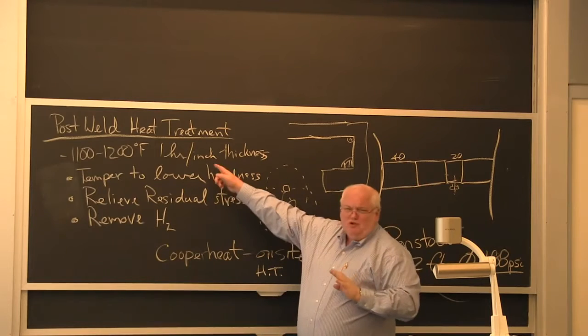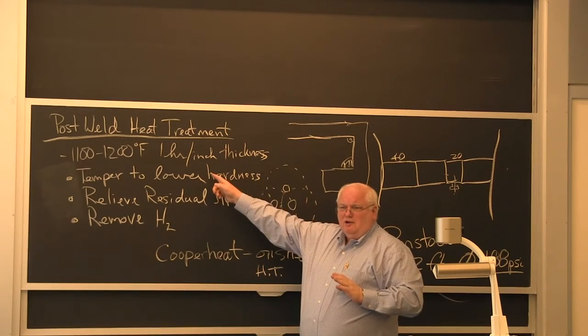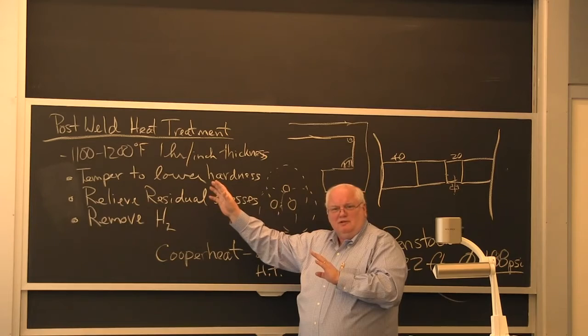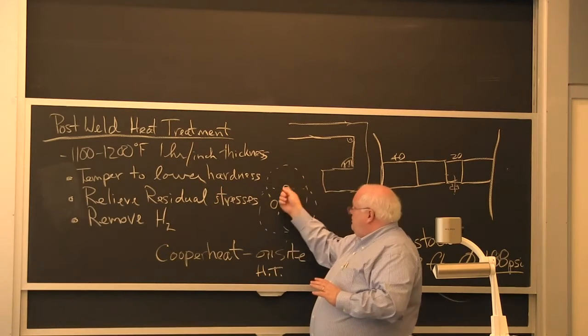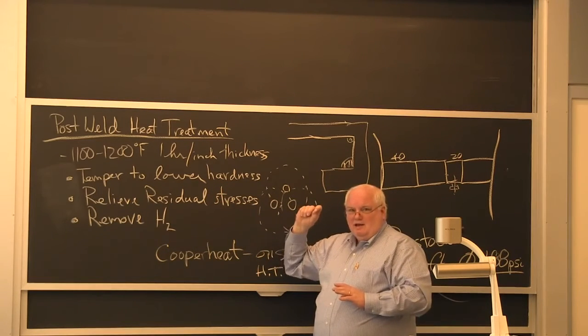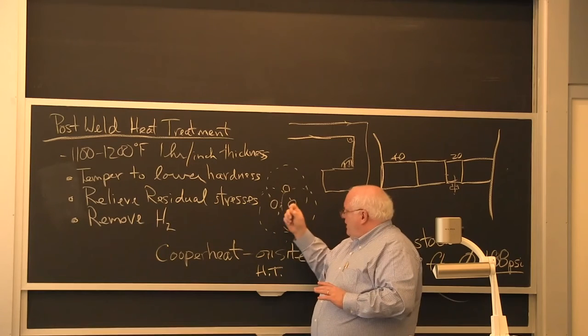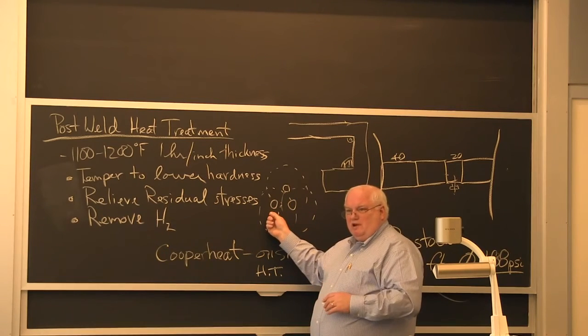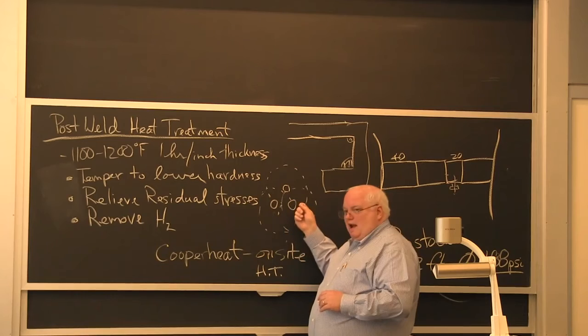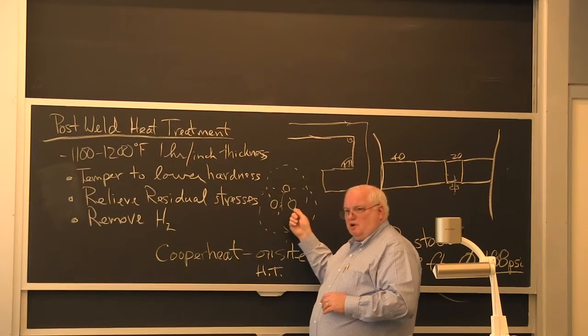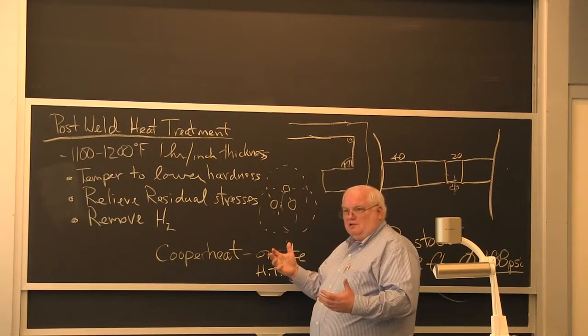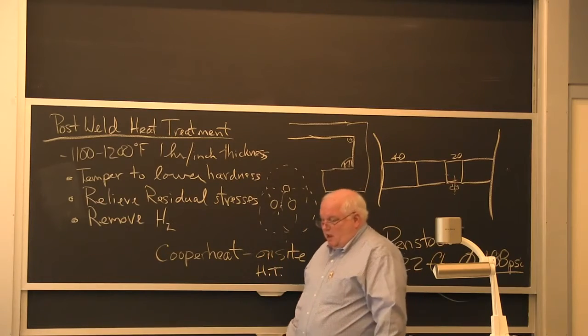Oh yeah, they were supposed to post-weld heat treat this, according to the code, but they didn't bother to, okay? So it had plenty of residual stresses. They hadn't done the post-weld heat treatment. It probably had plenty of hydrogen because they didn't preheat it properly. And it had a high hardness microstructure because they didn't preheat it properly. So they did about everything wrong you can imagine.